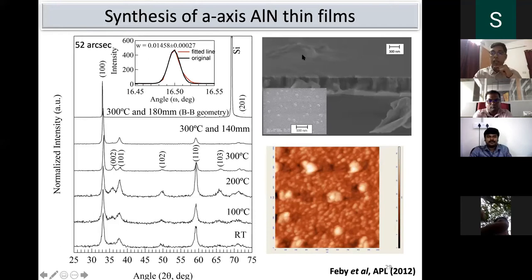Interestingly, this is a layer and island growth. That's why you can see small dot-like features. This is the island, and this is the covered layer. This is atomic force microscopy, and this is scanning electron microscopy, the same image. From this, we can understand. This was published in APL in the year 2012.